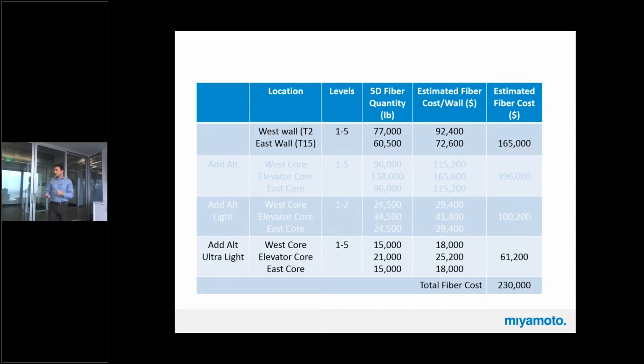And you may say, okay, how much does it cost? Fiber itself is not expensive. For the whole building, we calculated that it is around $1.2 per pound, and that the fiber cost would be around $230,000. It reduces the slump a little bit. You need to add some high range water reducer to the concrete, and you need more effort for pouring that. But fiber itself is not expensive, and with a low amount of fiber, you can reach high performance in this structure.